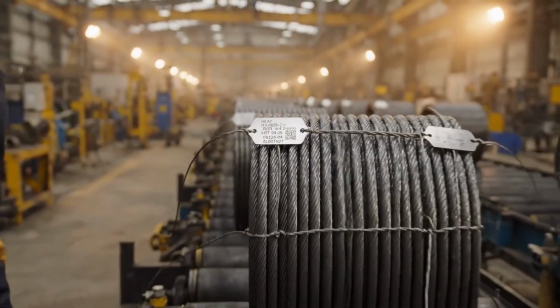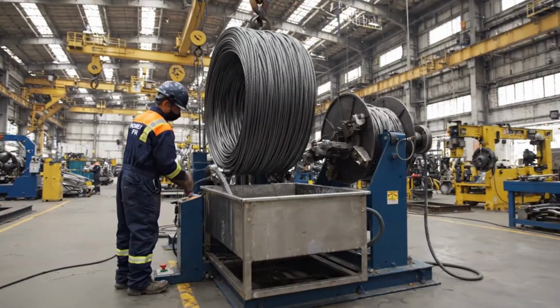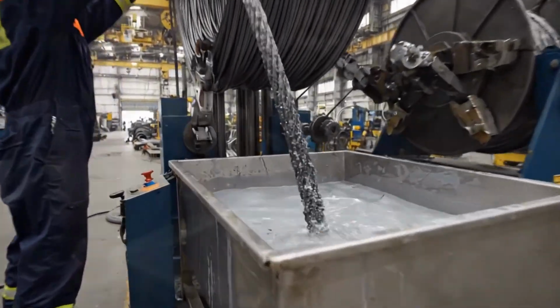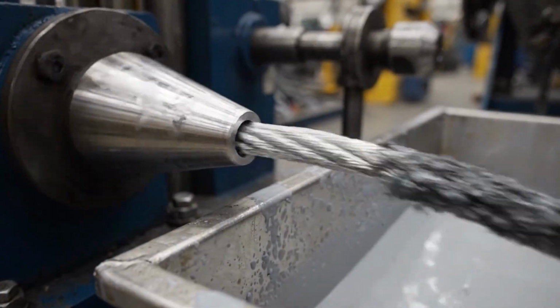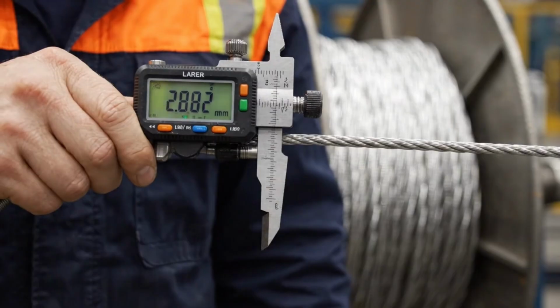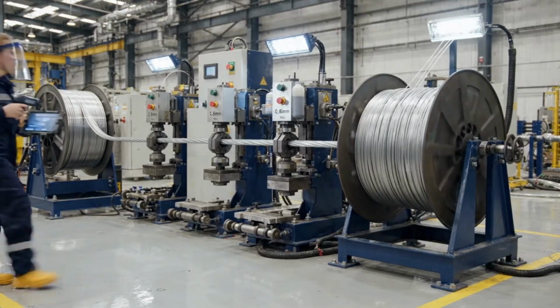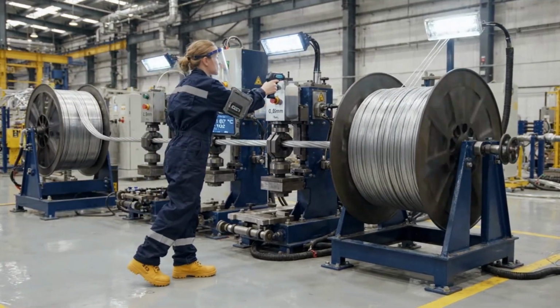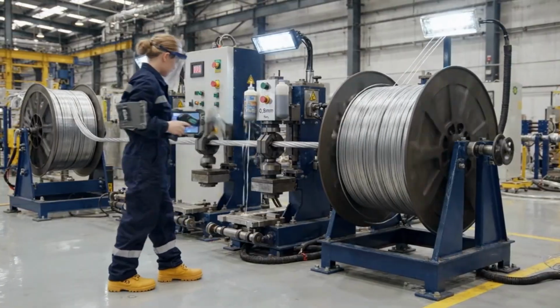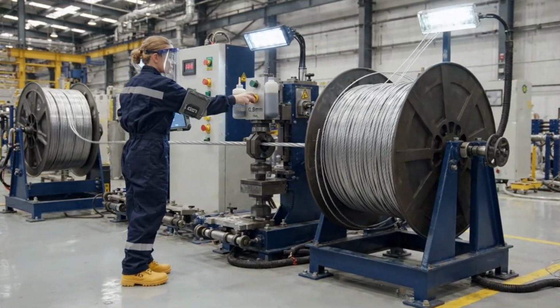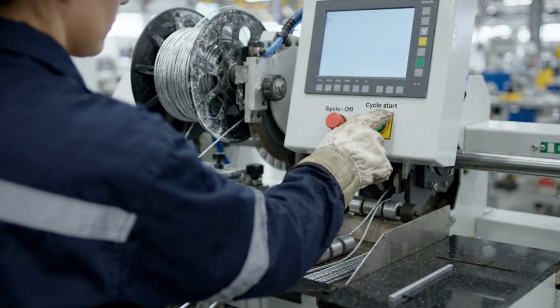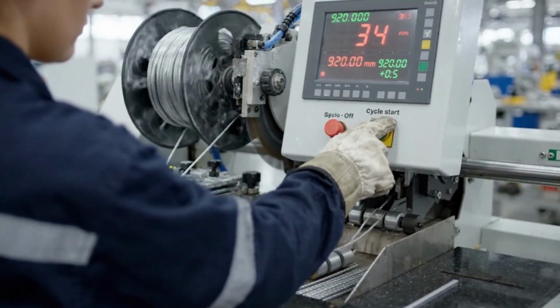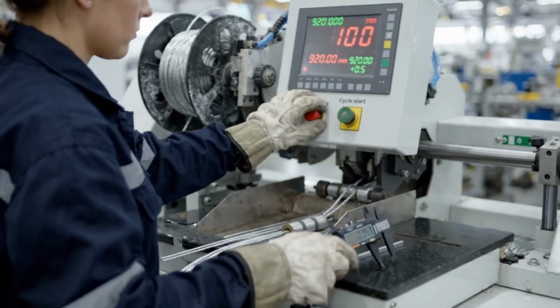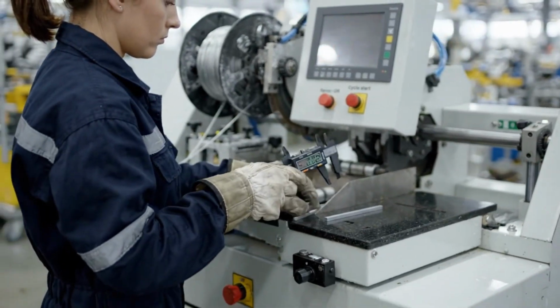The first draw pass reduces the cross-section by 56%, an elongation that aligns the grain structure along the wire's axis. The third draw pass brings the wire to 950 microns, a diameter at which the grain boundaries are aligned within 2 degrees of the wire axis. Cut to 920 millimeters, exactly the length needed to allow for tip grinding, barb cutting, and heat treatment distortion.